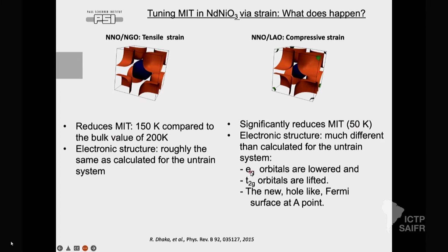Of course, what happened is that the eg orbitals are lowered, the t2g orbitals are lifted up, and as a consequence the new hole-like Fermi surface at the A point is formed. So this is our work from 2015, and we think that in this way we close what strain can really give us in the MIT picture.